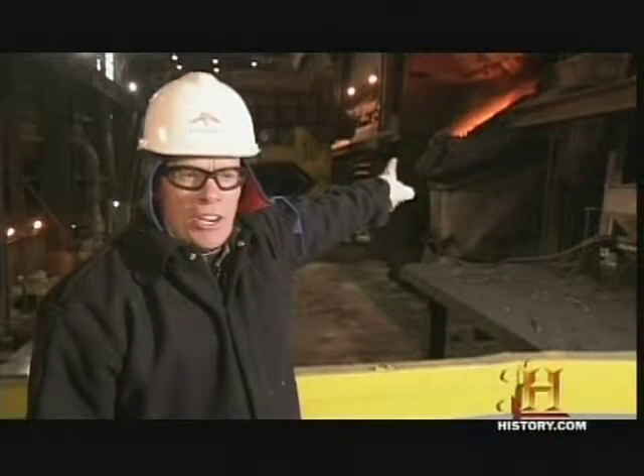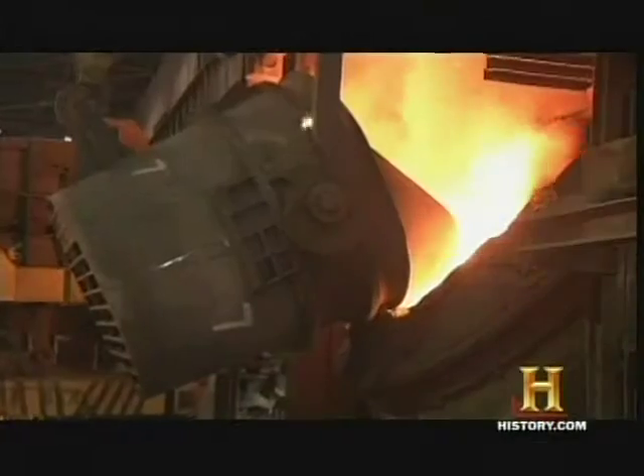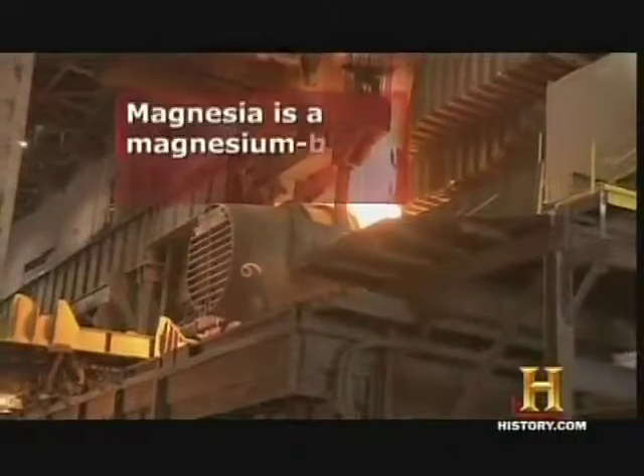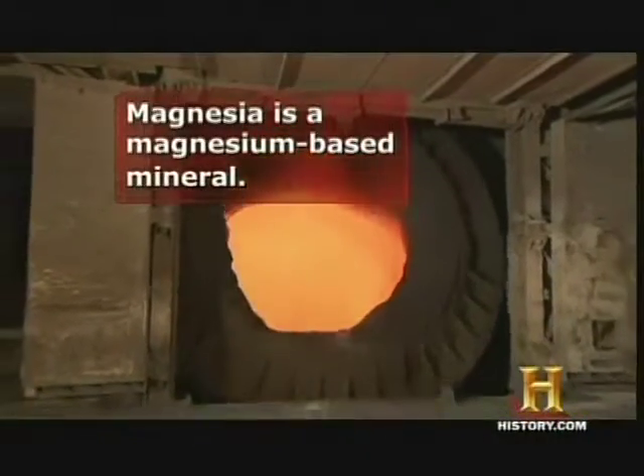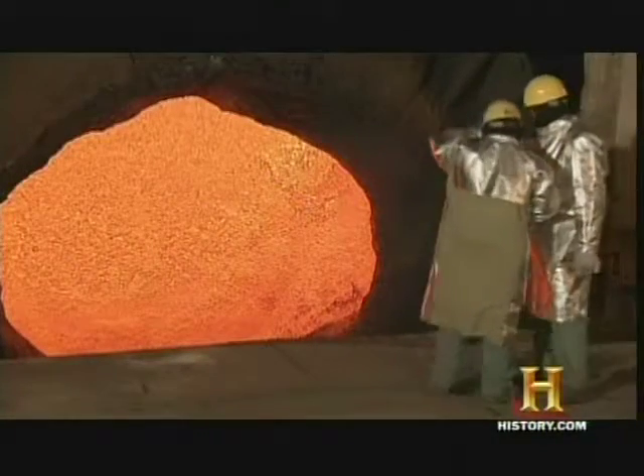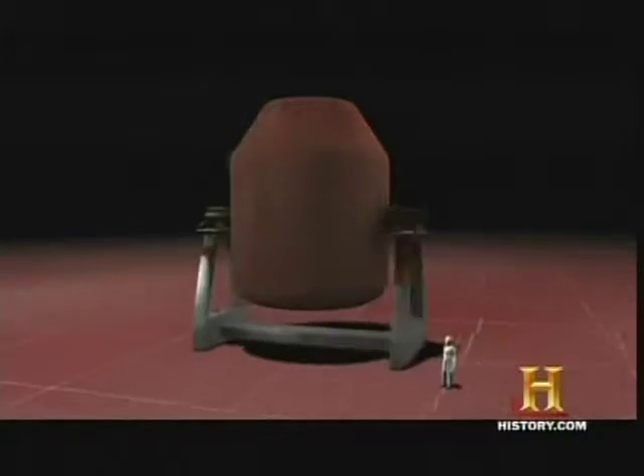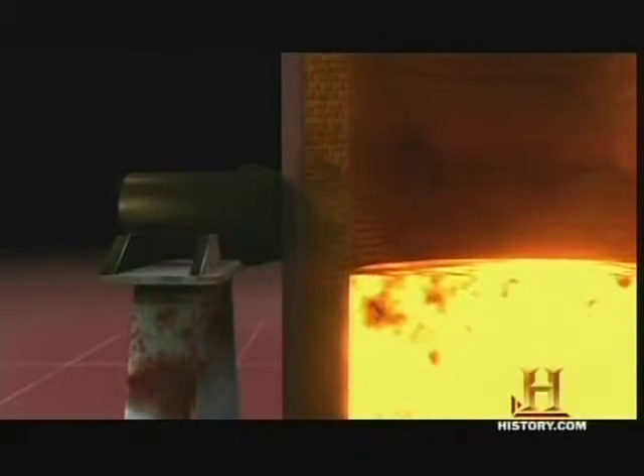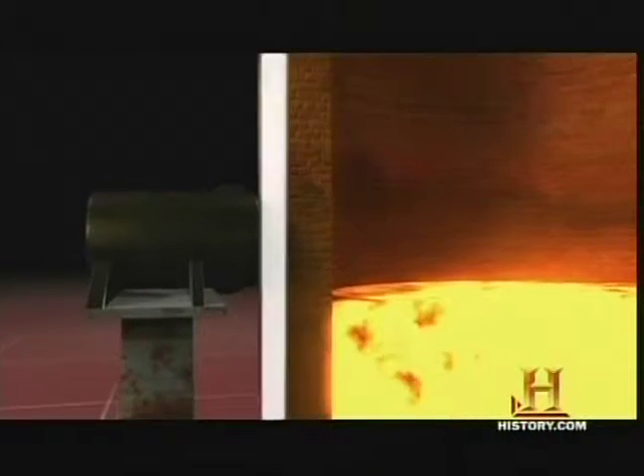Behind us here, you're seeing our #1 furnace at the Burns Harbor Steel Shop. In the furnace, a magnesia carbon lining is the protection of choice. The combination of magnesia's high melting point of roughly 5,400 degrees Fahrenheit and carbon's strength make them ideal for taking on the super hot. It's about $1.5 million worth of brick, and that brick acts as an insulator between the 3,100 degree steelmaking temperatures and the steel shell on the furnace. On the outside, the shell is between 300 and 350 degrees Fahrenheit.